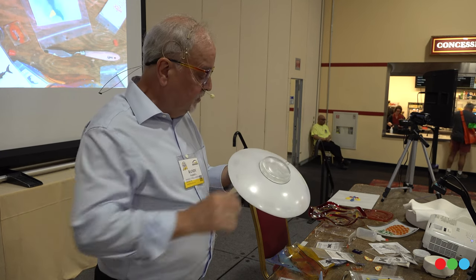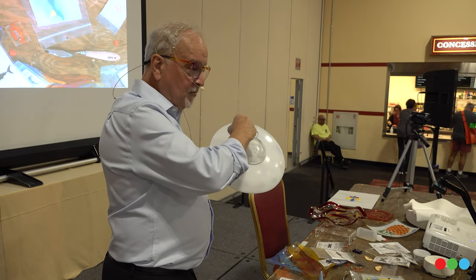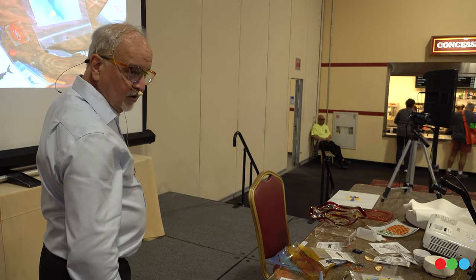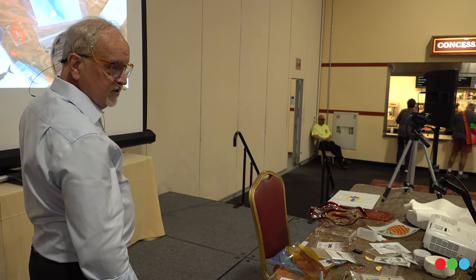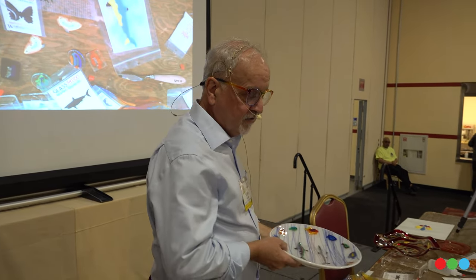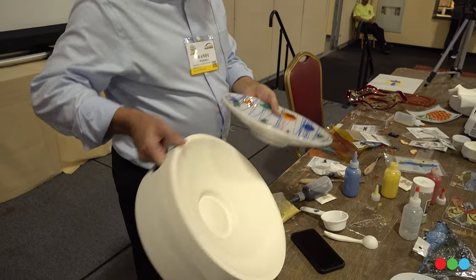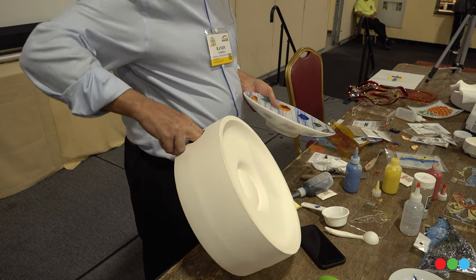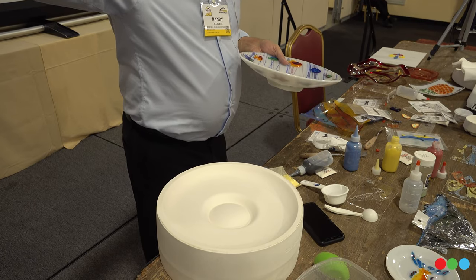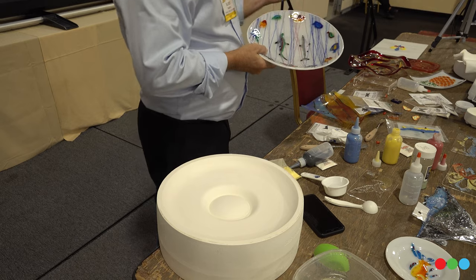Rather than see that as a bad thing, I like that. But if you don't like that, all you have to do is take it up to 1,425°F and the whole thing will go completely flat. The hotter you go, the more bleed you get on the color, so the edges aren't quite as sharp — because all of the glass is now starting to melt together. Then you put the design disc on top of it and slump them — the top disc slumps and touches down on that foot and sticks at the same time. It creates a little cavity all the way around the edge of that foot, and all you have to do is wrap a wire inside that cavity and twist it at the top to hang it on the wall.